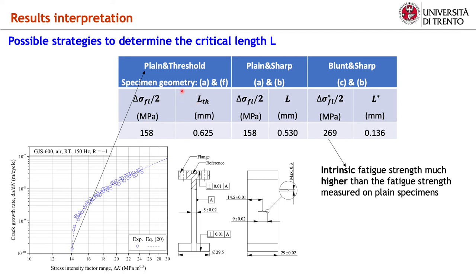This table lists the plain fatigue strength and the critical distance evaluated according to these three possible approaches. To apply the first approach, plain and threshold, the crack growth threshold was determined from fatigue crack growth experiments performed on a plain specimen. It can be noted that the two approaches based on the plain fatigue limit predict a very large value of the critical distance, above 0.5 mm, well above the values typically reported in the literature for structural metallic materials. Conversely, the approach blunt and sharp, based on two notch specimen geometries, estimates a much shorter critical distance, about 0.14 mm, and an intrinsic plain fatigue strength, about 270 MPa, significantly higher than that displayed by plain samples that we know to be affected by microporosity.